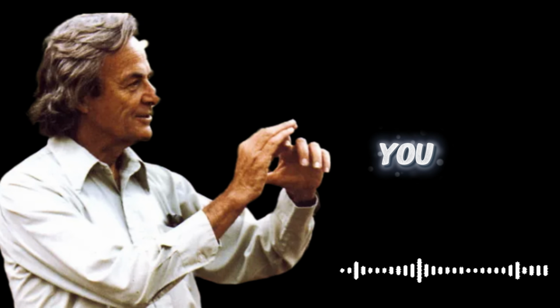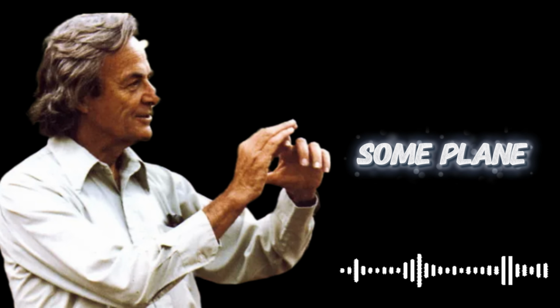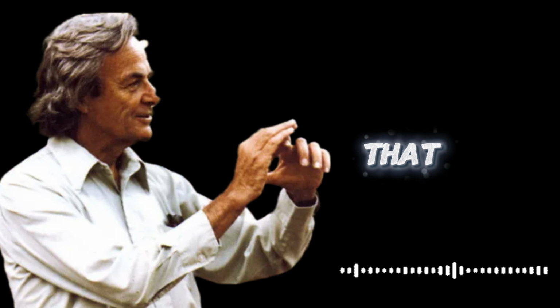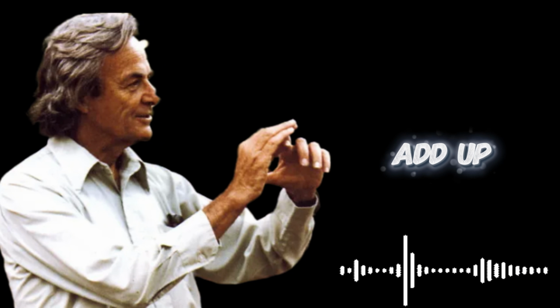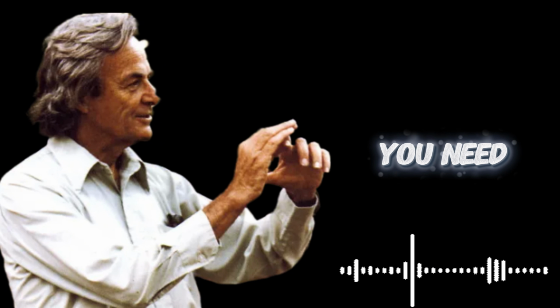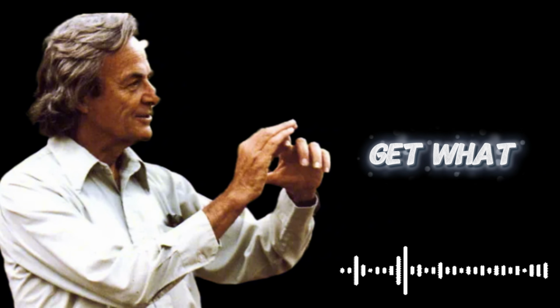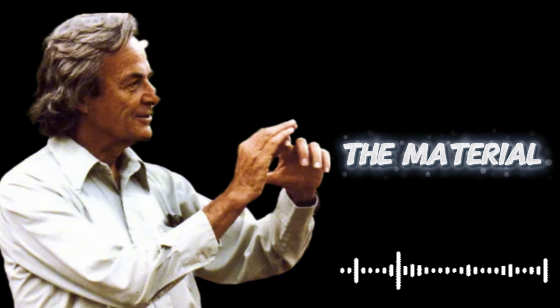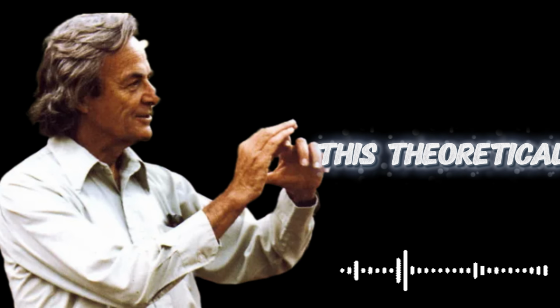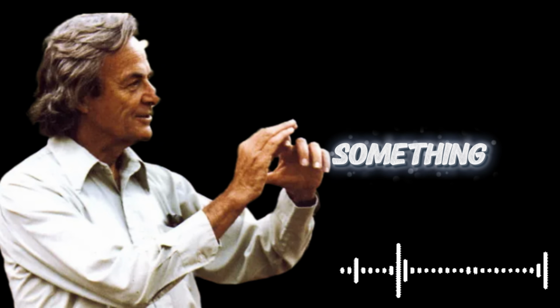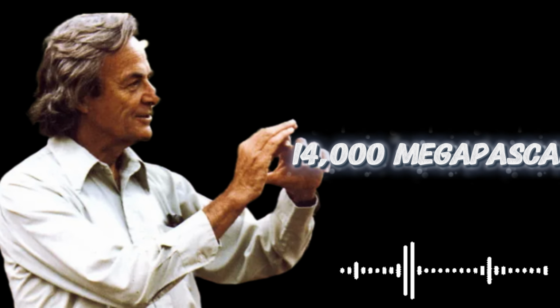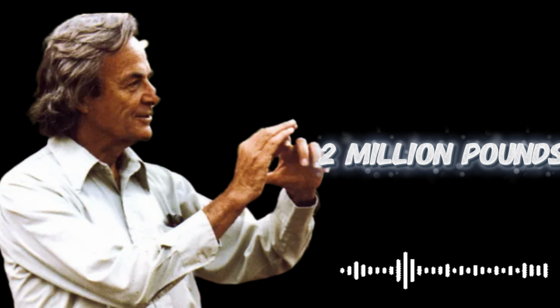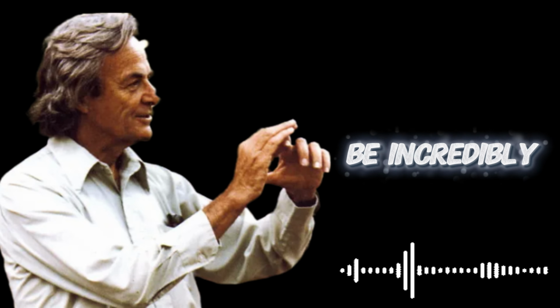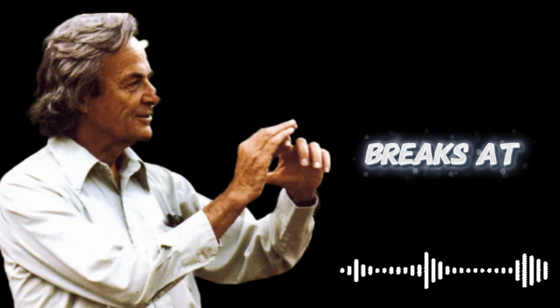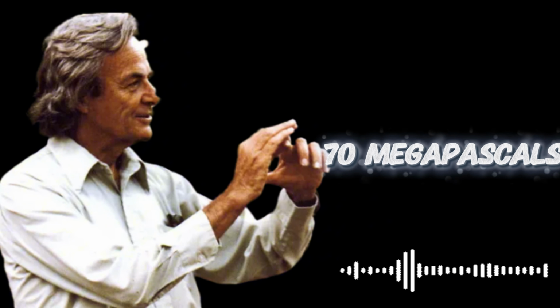To do this, you need to break the atomic bonds across some plane inside the material. How much energy does that take? You can calculate it. Add up the bond energies for all the bonds you need to break across that plane, and you get what we call the theoretical strength of the material. For glass, this theoretical strength is enormous, something like 14,000 megapascals. That's about 2 million pounds per square inch. Glass should be incredibly strong, but here's the problem. Real glass breaks at stresses around 70 megapascals.